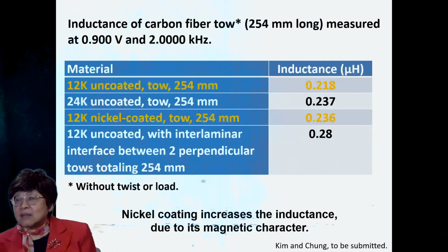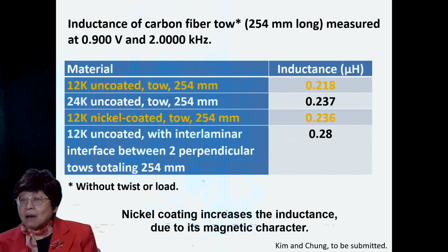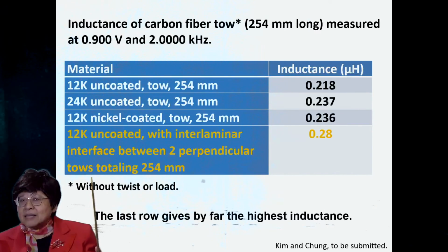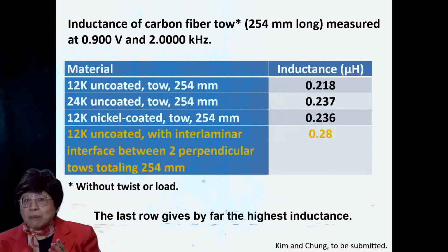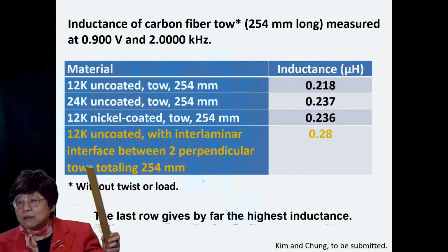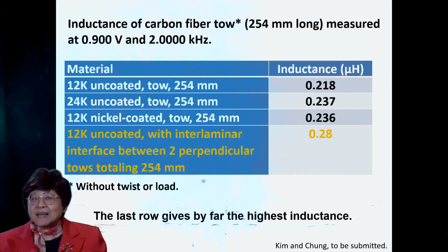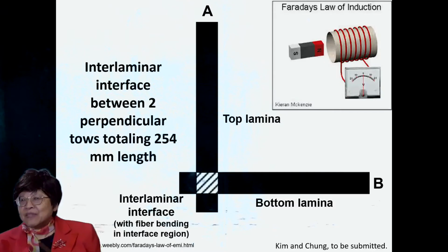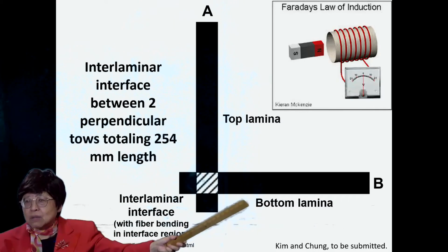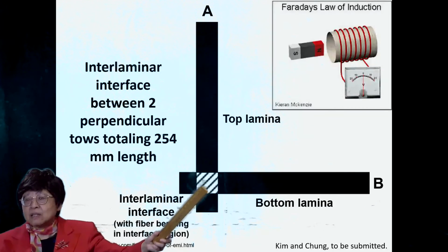Comparing uncoated carbon fiber versus nickel-coated carbon fiber, the nickel coating increases the inductance, and that's due to the magnetic character of the nickel. The bottom case is that of the uncoated fiber involving two tows that are perpendicular to one another and overlapping to form an interlaminar interface. And this configuration gives by far the highest inductance. And this is that configuration. You have two tows, two laminae, perpendicular to one another and overlapping here, and this is the interlaminar interface, and we have epoxy there.